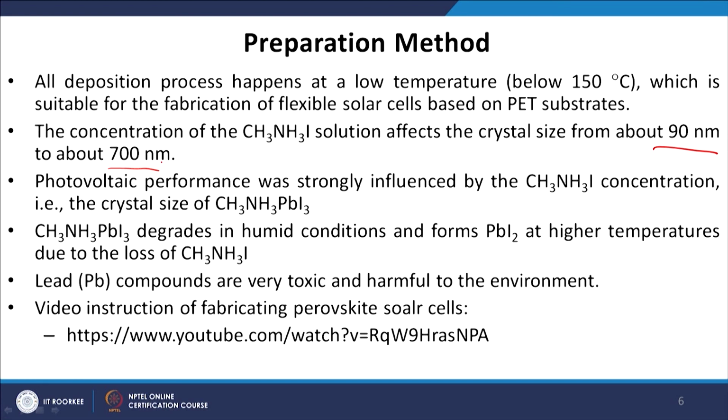We already discussed that CH3NH3 lead iodide is a 3-dimensional crystal structure. If you heat it, what will happen? CH3NH3I leaves the crystal structure, leaving only lead iodide in your sample substrate, and one can experimentally prove that. So these materials are not very stable under higher temperature.